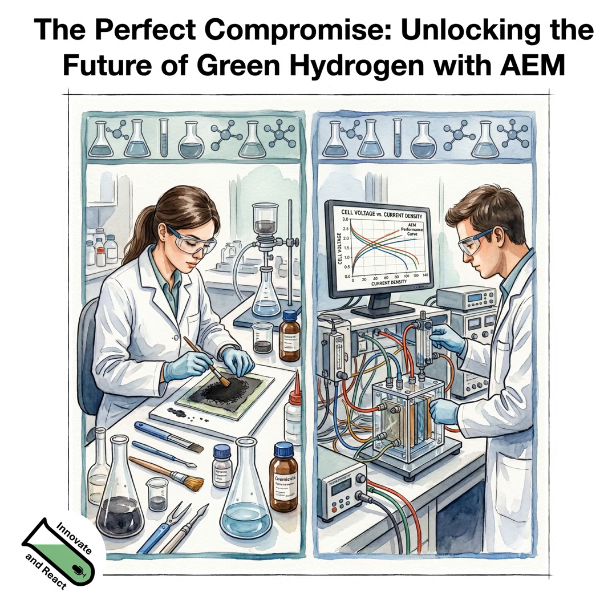Mostly we look at the element distribution of nickel and iron, for example, and also sulfur, and how homogeneous the catalyst layer is on the surface. And mostly, we do the electrolysis test and look at the activity and the stability during our electrochemical measurements.